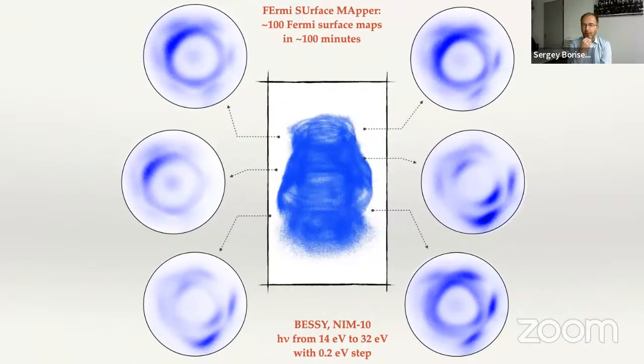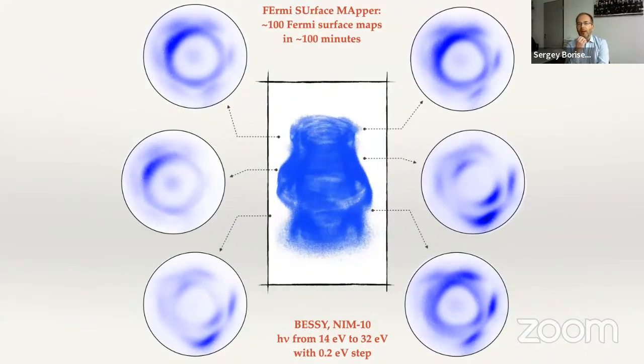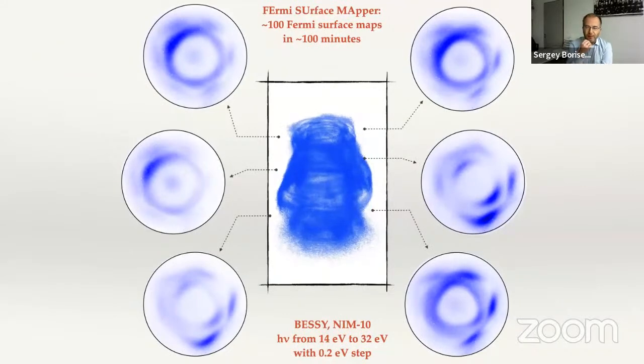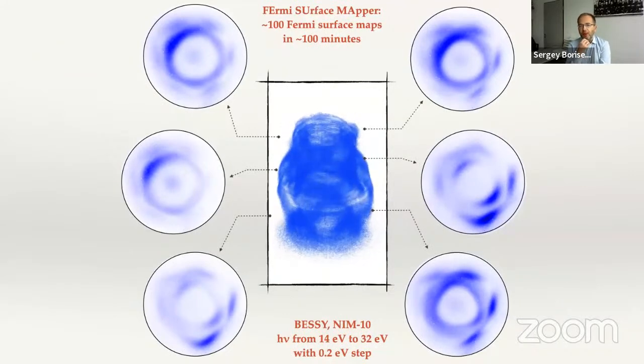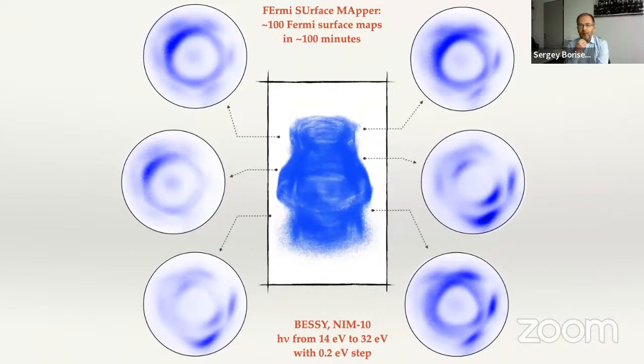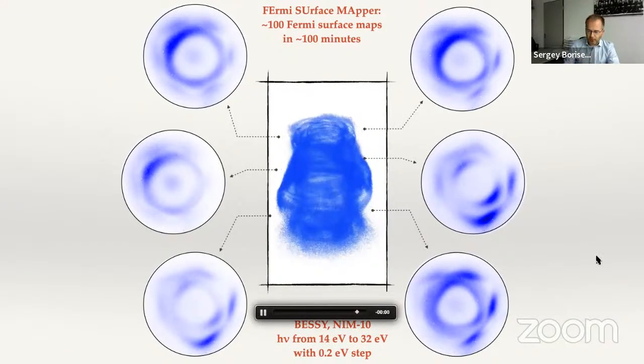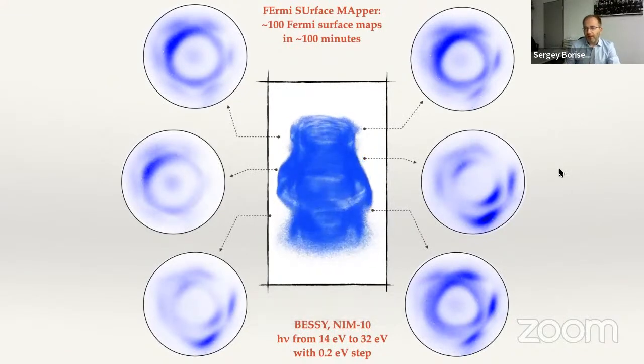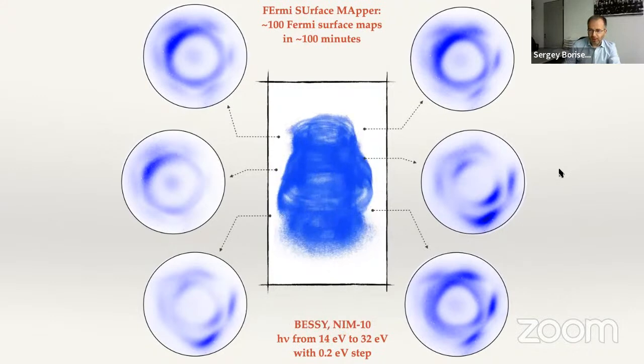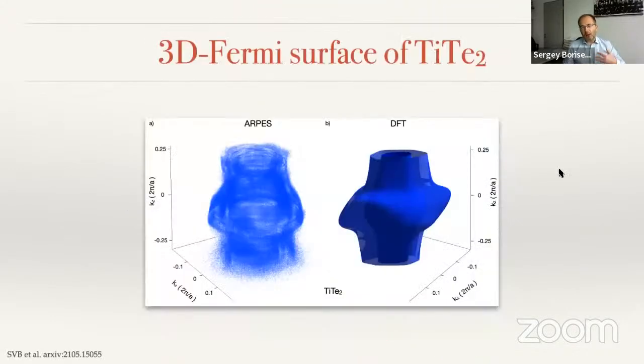And this is an example. The data were taken at BESSY. We measured approximately 100 Fermi surface maps within 100 minutes, meaning each of these maps took about 1 minute. Then you have access to the three-dimensional Fermi surface, which you can compare to the DFT calculations and consider all details.